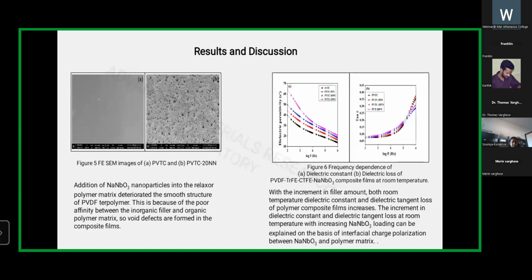And coming to the morphology of the nanocomposite films prepared, we can see that the morphology of the pure films changed with the filler addition. That is one of the main characterizations of solvent casted film. And the electrical study is mainly done using dielectric properties, and dielectric properties of the composite films improved with the filler addition. That is actually one of the main characterizations of the solvent casting process, and it is mainly due to the interfacial charge polarization between the filler and the polymer part.